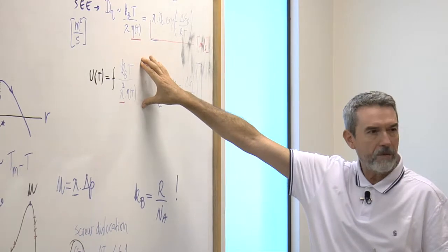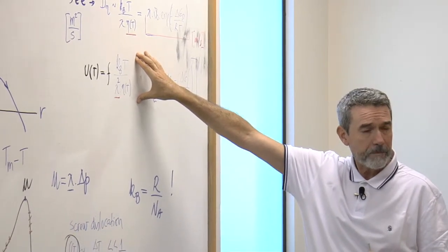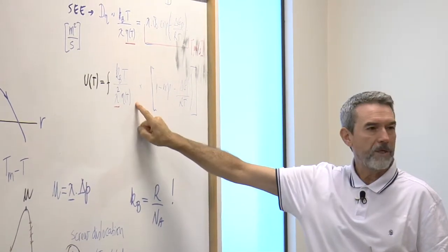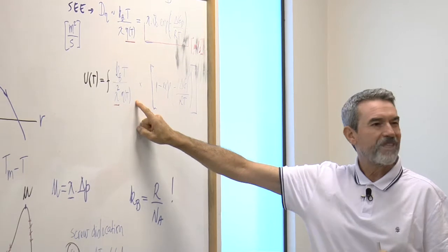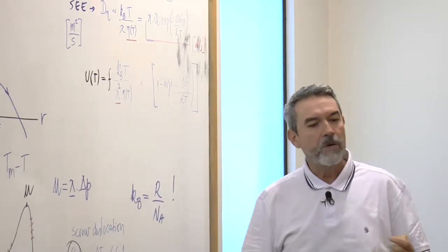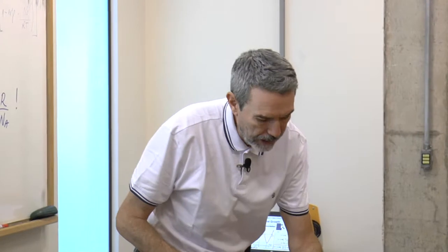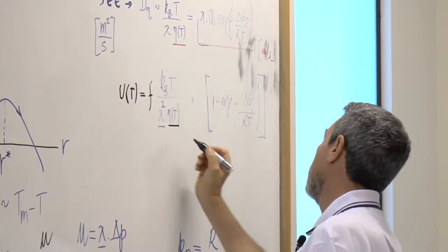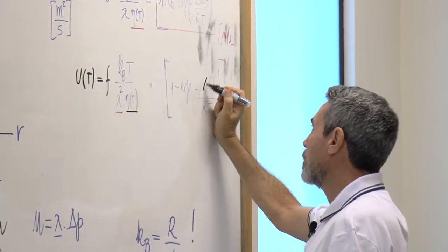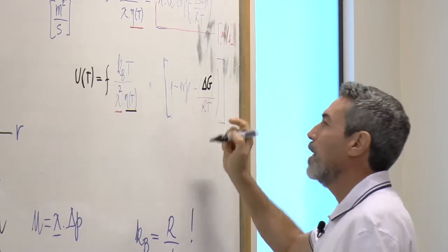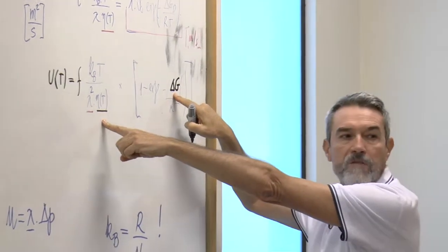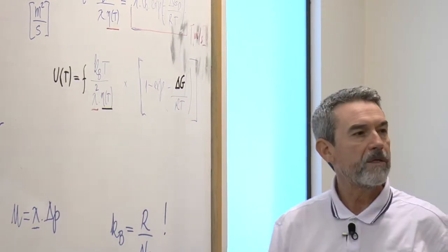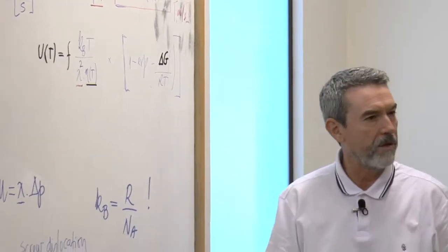You're going to try to fit experimental data to your adopted glass using this equation here. And for such a test, the controlling parameters that you need are the viscosity and delta G. You already have the viscosity and delta G because you have used these two parameters to test the classical nucleation theory.